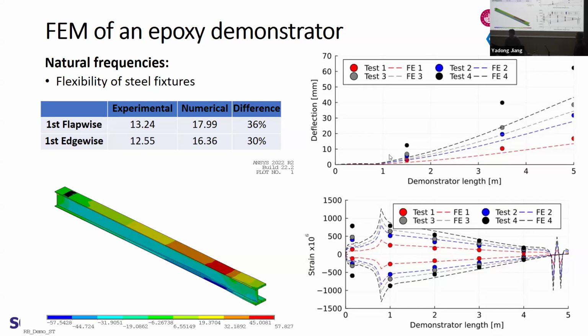And in terms of the prediction of the strain and the deflection, for deflection we see good agreement in the first 3 load cases, because for those load cases we don't have any damage in the composite material, and we can have a good prediction. In load case 4, since there is internal damage, mainly on the steel insert in the root, there is a slightly larger difference between the test and the numerical prediction.